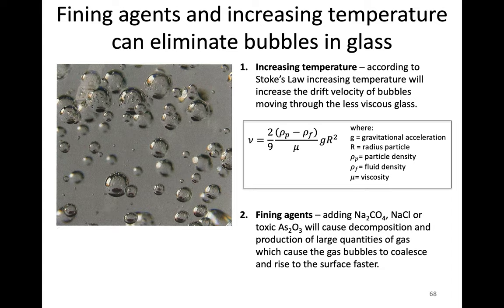The other way is by adding what we call fining agents—something like sodium carbonate, sodium chloride, or even arsenic oxide, which is, as it sounds, toxic. But what these do is when they go into very hot glass, they decompose to form CO₂ or various gases or oxides when they hit that hot glass.